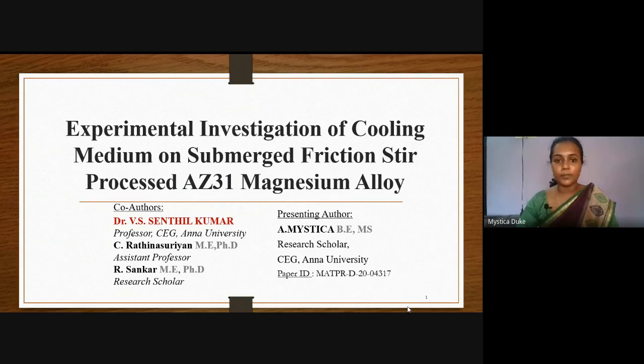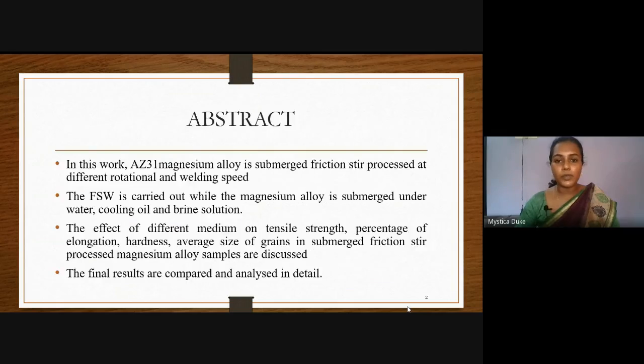The abstract of this work is that we have taken a magnesium alloy, AZ31, and we have conducted friction stir processing by submerging this alloy in 3 different media: water, cooling oil, and brine solution. Then we took these processed samples and analyzed the effect of these media on their mechanical properties. We also altered the rotational speed and welding speed of the friction stir processing.